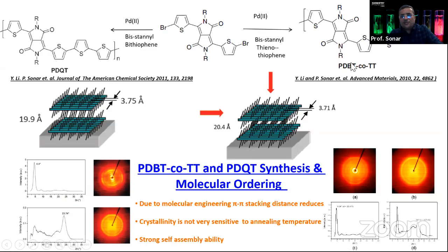And here you can see, as you take the closed structure versus this open structure, for the closed structure our pi stacking distance, which we calculated from this X-ray diffraction data by taking the second diffraction peak and using Bragg's equation, n lambda equals 2d sine theta, we got this value of d-spacing or pi stacking of those polymer backbones. This polymer usually forms two types of stacking. One is called face-on and another is called edge-on. So this is a typical example of an edge-on.